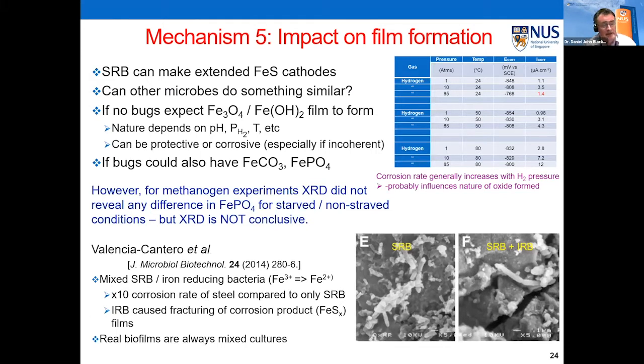But when we looked at the methanogen work, we couldn't see any difference in our XRD between the starved and the non-starved. But XRD is not conclusive, particularly as it can only really see a crystalline film. Quite often these films might be amorphous. But there was some work by Valencia-Cantero, I think that is, where they looked at SRB and iron-reducing bacteria together, and they found that that combination gave you 10 times higher corrosion rates.